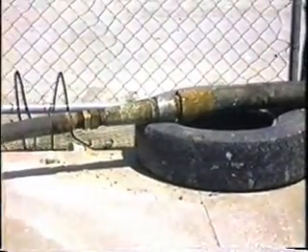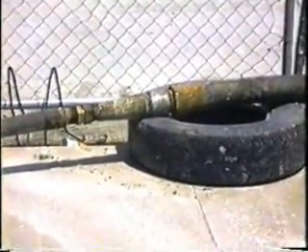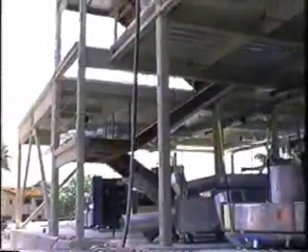on the standpipe size. Maximum hose lengths for different diameter hoses should be in accordance with those listed in the application manual. Tapered reducers must be used when a reduction in hose diameter is necessary. Metal standpipe 2.5 inch to 3 inches in diameter must be used when pumping height exceeds 3 stories or 36 feet or when required hose length exceeds 335 feet.